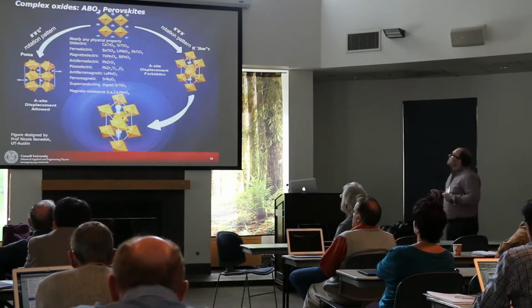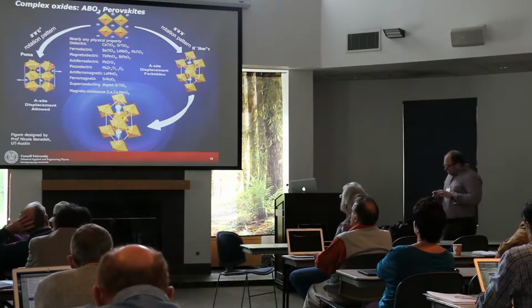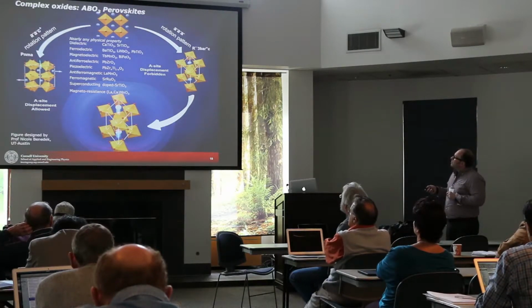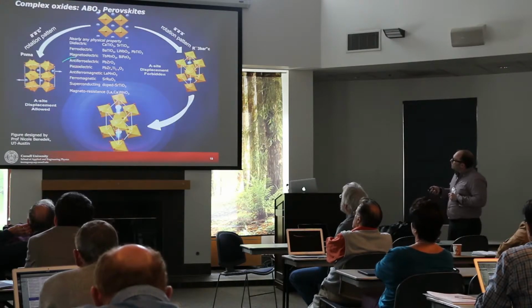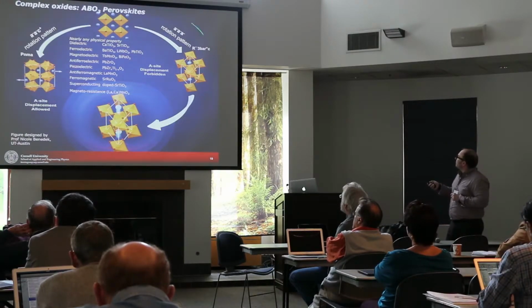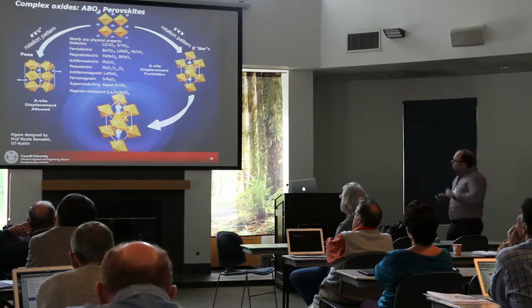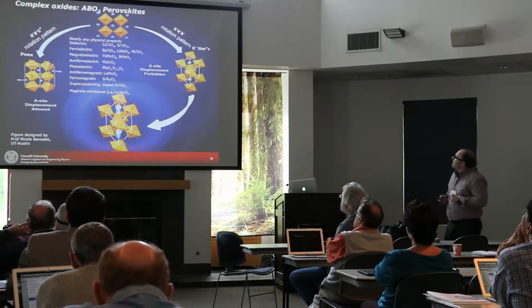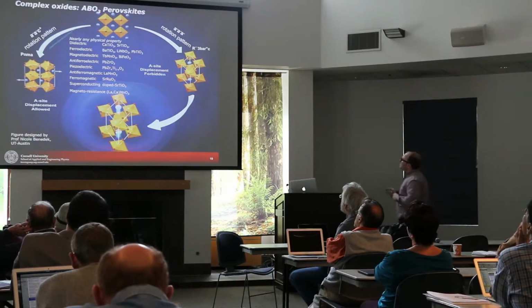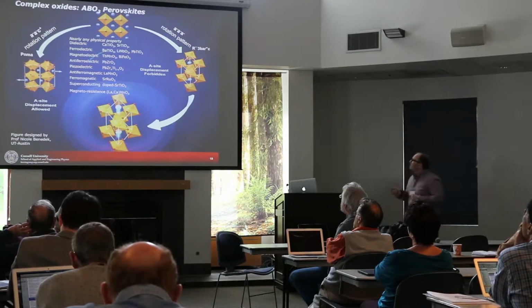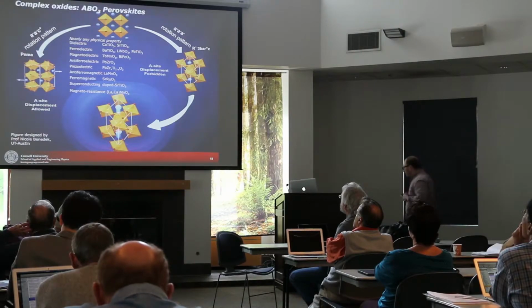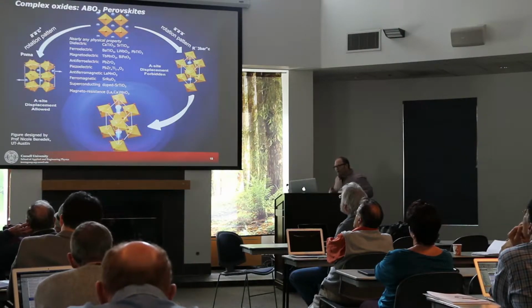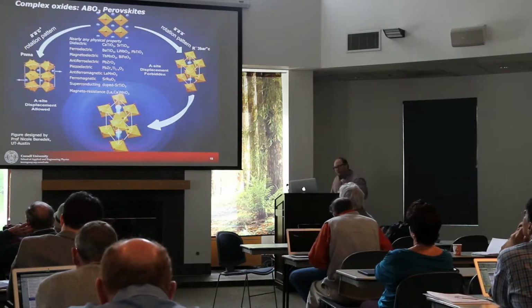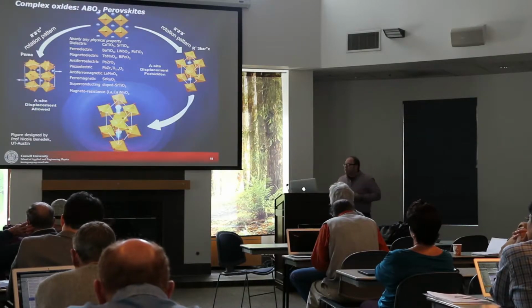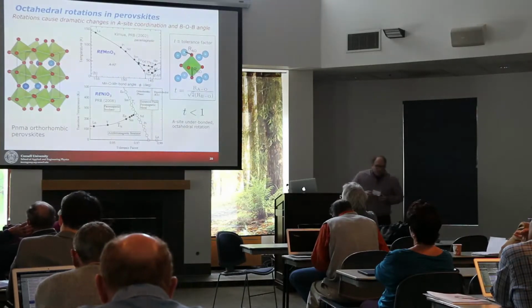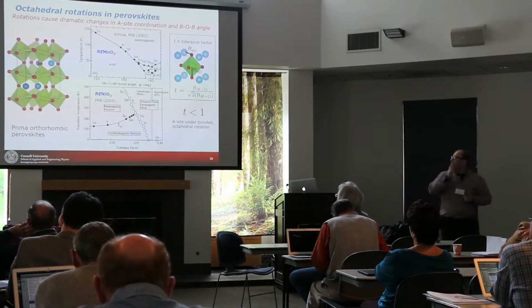Two common patterns are that these octahedra rotate. The two most common ones: here is one pattern known as the orthorhombic perovskite structure. Here is a rhombohedral distortion of the octahedra. And it's because of these rotations that we can accommodate all of these different cations. The reason why I'm harping on these very subtle and a lot of times small structural distortions is because, believe it or not, these very subtle distortions control the properties of these materials.